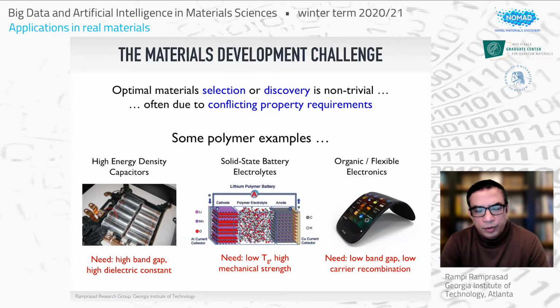And the item in the middle is a picture of a solid state battery electrolyte, where the solid state electrolyte could be a polymer, which can shuttle these lithium ions or ions from one electrode to the other. And for this polymer electrolyte to be a good electrolyte, it has to, of course, have a high ionic conductivity, which basically translates to the material having a low glass transition temperature. But it also has to have a high mechanical strength, for which you need a high glass transition temperature. You see, so again, you have two properties that are unfavorably entangled.